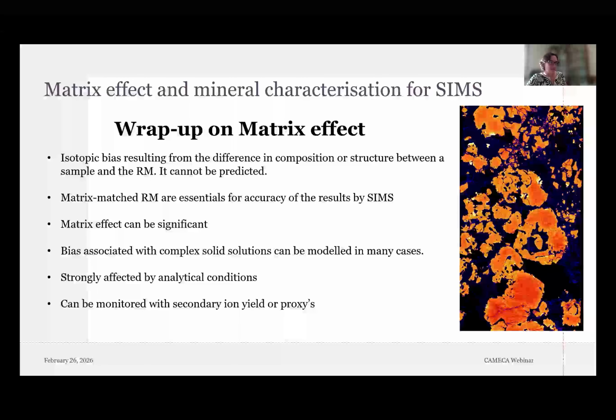So it is absolutely necessary to have matrix-matched reference material to ensure that SIMS results are accurate. This matrix effect is significant. It can be associated with complex solid solutions that are not always easy to model. This matrix effect can be affected by analytical conditions, but can be monitored by looking at ion yield and also proxy elements.